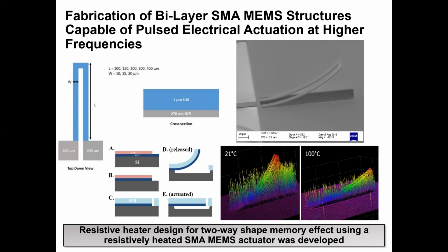mask plate. It was the large CTE mismatch between the NiTi and SU8 combined with the high temperature curing of the SU8 that caused these interfacial strains to develop at the interface, which ultimately caused the bilayer MEMS device to curl upwards upon release from the substrate.